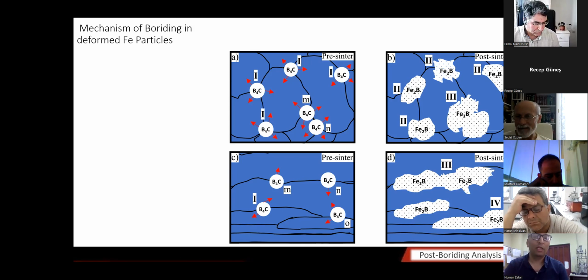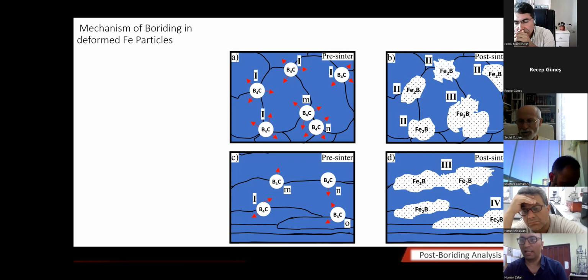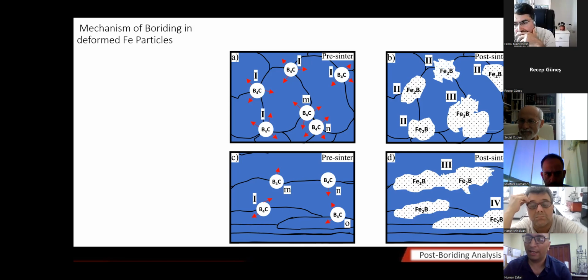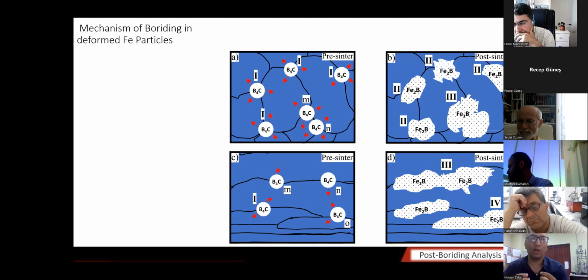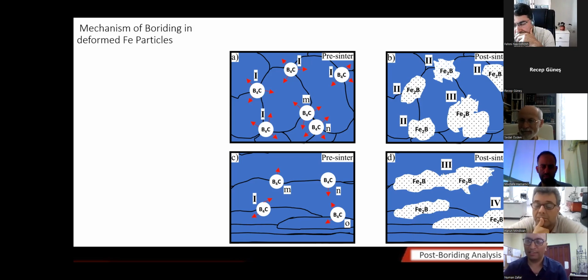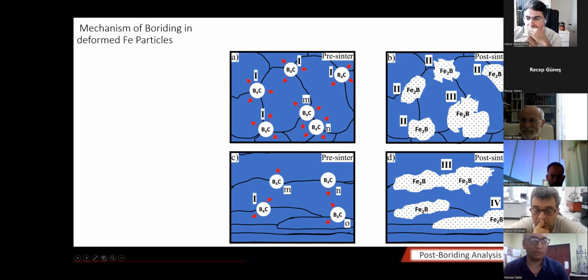You are saying that it is not correct to claim that the hardness of the core is increased, because B4C has a higher hardness and Fe2B has a little lower hardness. Should be, I mean, yes, that is my guess. But the B4C particles used in the core were so small that I would need a micro scale indenter to measure their hardness. And B4C particles are not there to increase the overall strength of the wires. They are there only to serve as a boron host. That is their role in this state. After their role is completed, and because they are small, we have been able to synthesize these iron boride phases, and I think their role is finished. Very good, that was the purpose.